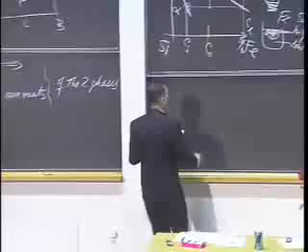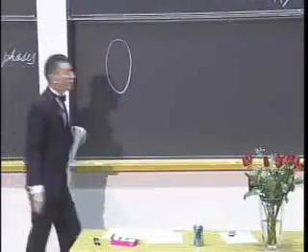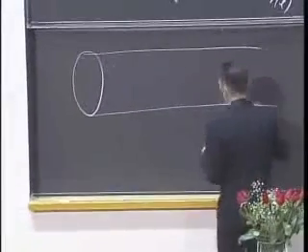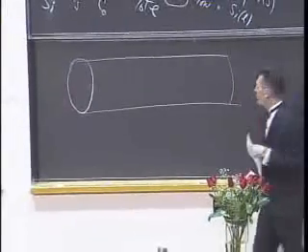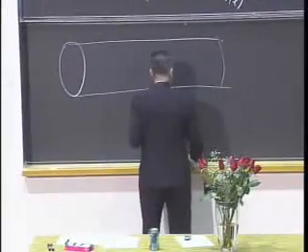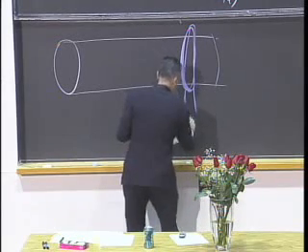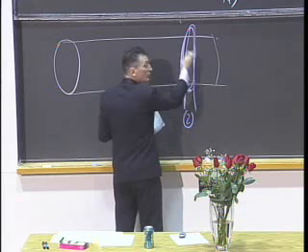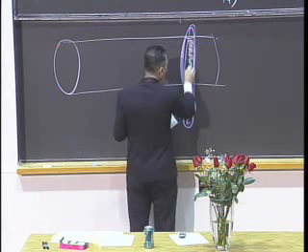You take a giant salami of silicon, which now the standard is 12 inches in diameter. So this thing is a single crystal of silicon, 12 inches in diameter and several meters long. So we're not going to take that single crystal and remelt it. What we can do instead is put some induction coils around it. If we put induction coils around it and send a current through it, what will happen is this will get so hot that it'll melt, and by surface tension forces, I can contain the molten zone here.